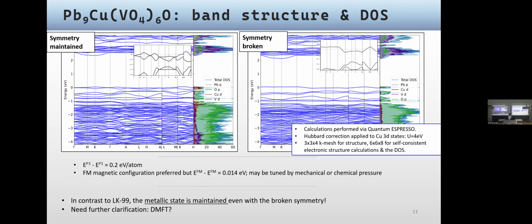So here, this approach of symmetry breaking was applied to the next candidate material that we decided to consider, the vanadate lead apatite with copper. Vanadate in particular was considered because it was experimentally synthesized before and also characterized in the literature. The discovery based on the density functional theory calculations was basically that in this case, even after the symmetry breaking, the metal state persists, meaning that the bands still cross the Fermi level. Of course, this is not a definite result, because with those tricky systems DFT may be misleading, as we know, but still, those are the first findings.